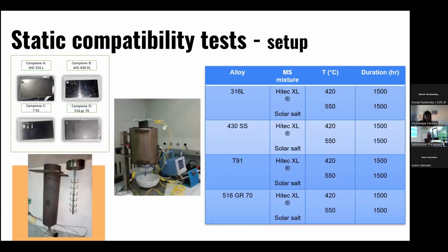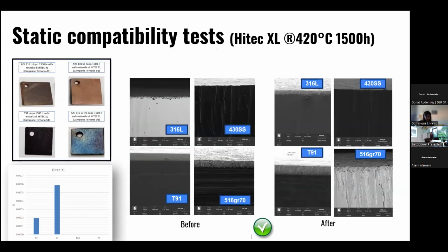So just a few words regarding compatibility test. We performed some static compatibility tests in a lab scale. Here, I want only to show you some highlights of our work. We decided to choose some representative steels that are the components mostly used in CSP plants: 2 austenitic steels, 1 ferritic steel, and 1 carbon steel. And first of all, we decided to perform some static test, inserting the salt in the setup that you see in the picture, and heated it up at different temperatures for this duration of time. And then we analyzed the salt, the mixture after the experimental campaign, just to check if there were some metals or some excess of something that could damage the composition of the salt.